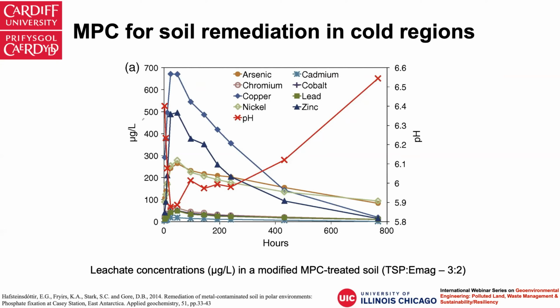But because MPC is based on acid-base reactions, it is less affected by the low temperature. So in this study, the reactive grade of magnesia is used with sodium phosphate solutions. And as we can see, this cement treated the soil quite successfully, decreasing the leachability of almost all of the heavy metals in this Antarctic soil.